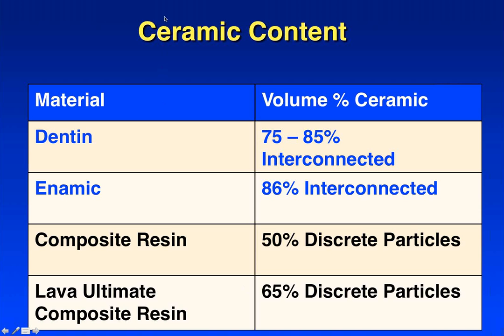If you look at the volume percent of the materials. Dentin, depending upon where you are in the dentin, it's again an interconnected hydroxyapatite network with collagen. Enamic is 86% interconnected. And then if you look at a conventional composite resin, maybe like a direct fill, you're between 45 and 50% discrete particles. All the particles are individual, and they're all surrounded by polymer. Lava Ultimate, which was an improvement over the MZ100, is still only about 65% discrete particles. So again, you still have a material where the filler is surrounded by a polymer. It's not interconnected like a natural tooth structure or the Enamic material.